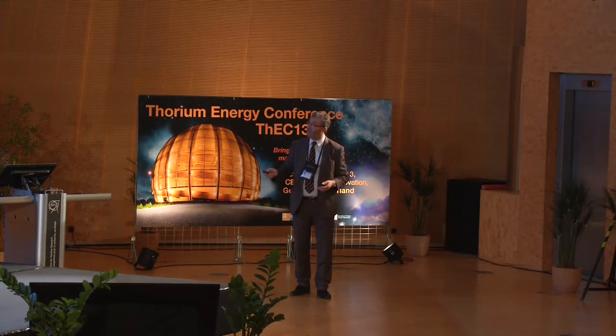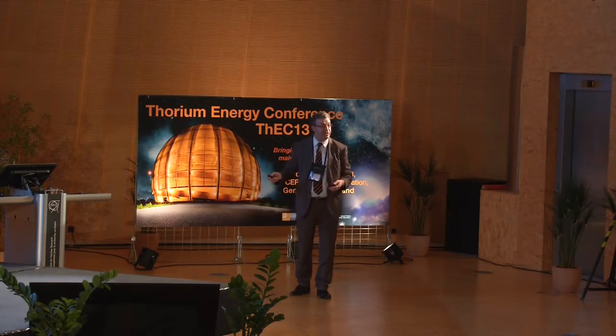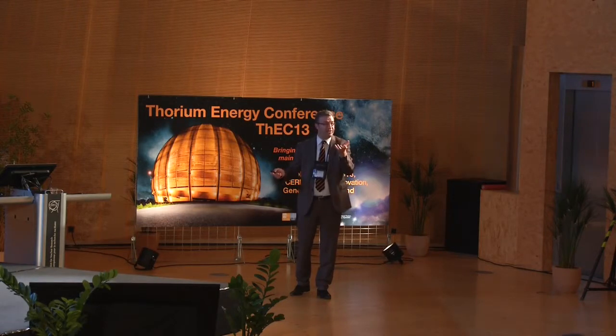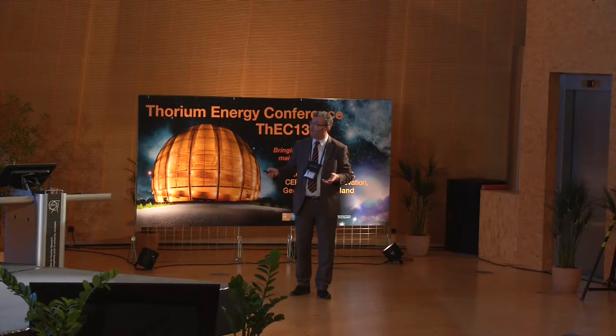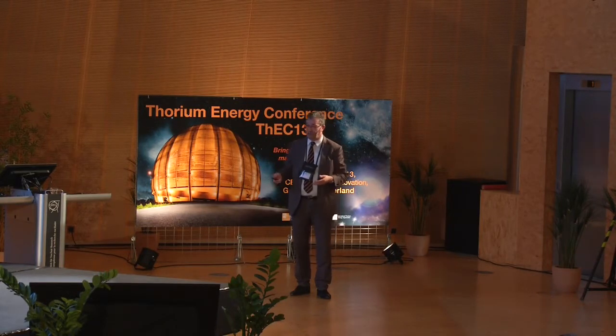And what you see is this. This is what IFMIF is intending to deliver. So the holy number for fusion people is 10 ppm helium per dpa. This is the characteristic of the spectrum. That's what they are aiming at. And with a dpa for the first wall, about 20 to 30 dpa per year. So this is the demo, what they are requesting for the first wall. And what we have seen and shown is that MYRRHA can deliver this kind of values and even go beyond, up to 25 ppm helium per dpa, and a range of dpa, which is this one.